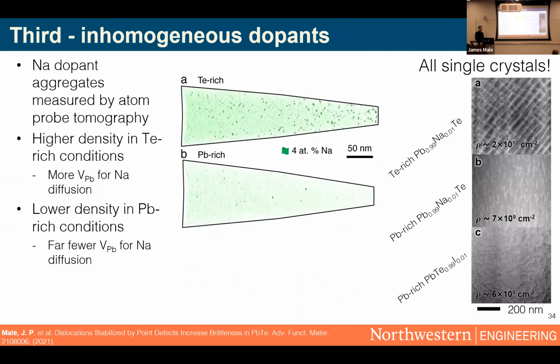Okay, and then the final key here is essentially the distribution of certain dopants in lead telluride. We see from some advanced atom probe tomography experiments and TEM that was performed at Aachen, Germany by Yuan Yu and Lamia, we find all this kind of aggregation of sodium dopants in our tellurium-rich sodium doped samples. All these little dots are essentially regions where sodium is in higher concentrations. And we would expect these all to be very difficult obstacles for dislocations.